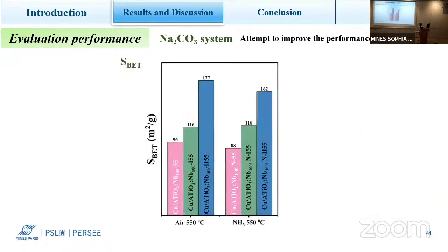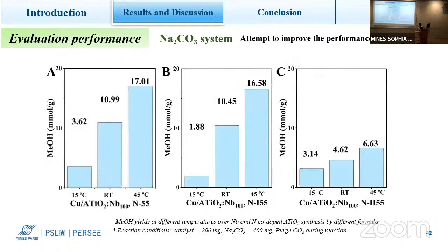Then we used BET to run nitrogen sorption. For the one I already used, after changing the solvent, the surface area increased a little bit. But for the last one, we had high expectations. It's almost twice my BET. So this one also has a way different morphology, and it has a really high BET. So we were thinking maybe this one is going to give good performance.